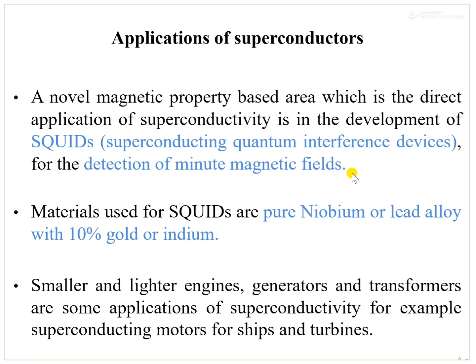Which kind of material could be used for SQUIDs? These could be pure niobium, or a lead alloy in which 10% gold or indium is mixed.